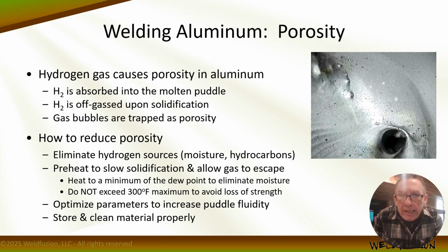You can preheat to eliminate moisture and slow the solidification rate of the aluminum. And this is one case where a little dab will do you. Preheats for aluminum need to exceed the dew point, right, in order to be the most effective at eliminating moisture as a source of hydrogen. And 250 degrees is really the maximum you ever need to go because it's well above the boiling point of water. So all that moisture should be removed from the material when it approaches that 250 degree mark. Preheats for aluminum should